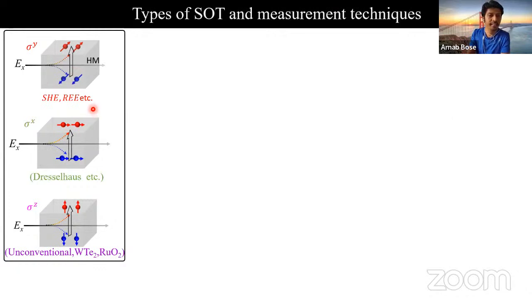So these are the three possibilities. In all the cases, we apply in-plane current and spins flow out of the plane from the generator to the adjacent magnet. The first one is very well known to us, that is the spin Hall effect or Rashba-Edelstein effect, where the accumulated spins are orthogonal to the direction of the applied current. We can also have a situation where the generated spins are polarized along the direction of the applied electric field. Such things happen in materials exhibiting Dresselhaus-like interaction.